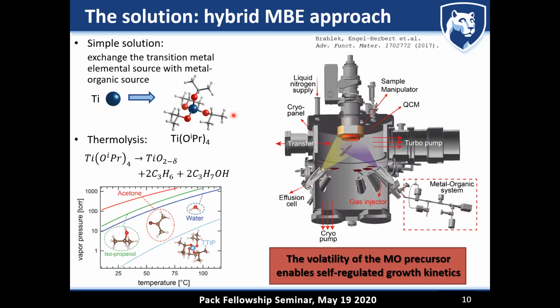We published on what the unintentional carbon contamination in a grown strontium titanate film is, for example. And what we find is that it's below parts per million. If you compare it 1-to-1 to a strontium titanate single crystal, which is easy because you can take a strontium titanate single crystal and grow a strontium titanate film by hybrid molecular beam epitaxy on it, you do a SIMS analysis, a calibrated secondary ion mass spectroscopy, and you drill through and look for your carbon contamination. What we found is that if growth temperatures are high enough for us, the carbon contamination of hybrid MBE grown films is actually smaller than what the bulk single crystal is. So it is a concern, and one has to keep track of it. We've done this. Typically, as growth temperatures are high enough, it is not going to be your concern right now.